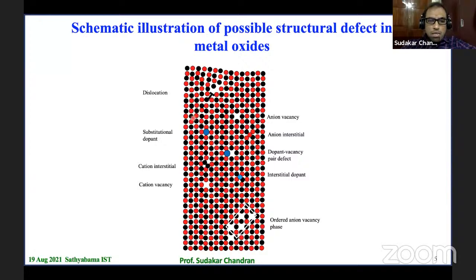In between the anions and cations you have gaps, and the dopants can fill up those gaps and produce a little strain. It is like on a school bench where 3 students are supposed to sit, and we try to squeeze 5 of us onto the same bench. Somehow we accommodate. Similarly, the lattice accommodates extra atoms in these interstitial sites. Sometimes the cation or anion vacancies can order in a structurally ordered fashion. Therefore, it produces a vacancy ordering. Sometimes it could be localized, or sometimes it could be everywhere. Therefore, it becomes a new phase.